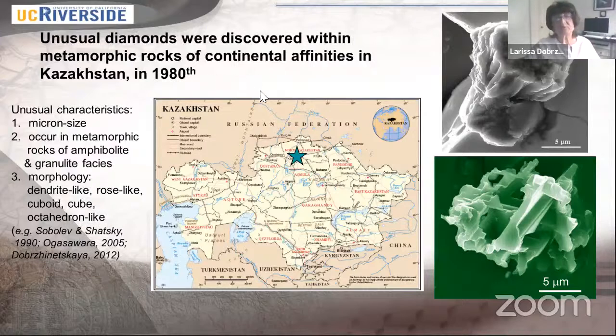So how did it happen? Geologists were doing a geological survey and mapping this territory. They were processing rocks, and they found in the heavy mineral fractions unusual minerals which appeared to be diamonds. But they were so small, only micron size. They were visible only under the microscope, and practically nobody believed that this was real diamond. However, scientists took this diamond for evaluation, and yes, they confirmed it was diamond. So, the unusual characteristic of this diamond, as you see on this image, is 5 micron size. So only micron size. They occur in metamorphic rocks.